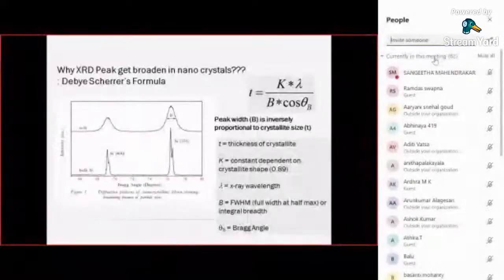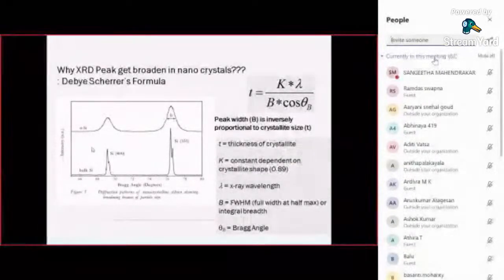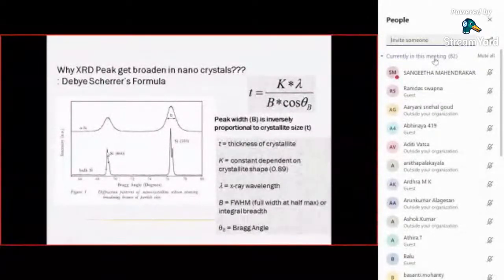When we see the nanomaterial and the bulk from XRD, X-ray diffraction, and we say this is the bulk silicon and this is the nanosilicon particle, what is the difference between the peaks? Peaks get broad in case of nanomaterial. But in case of bulk, there is no broadening. The width can be calculated by using the Debye-Scherrer formula in case of nanomaterial.